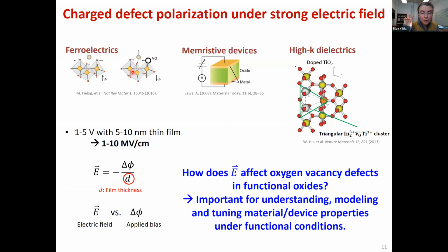And there will be two ways that these electric fields couple to the properties and stability of charged point defects. One is electrochemical, and I will indicate that in the thermodynamics. And the second is really the strength of the electric field that will give rise to polarization of charges associated with the point defect. And the fields that we are dealing with in such thin film devices can go to the order of 10 megavolts per centimeter. So these are indeed very large fields where electronic polarization in the material is reasonable to expect.